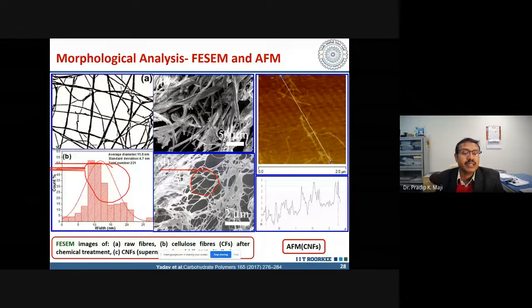Then we have done morphological analysis and diameter calculation. Average diameter we have come up with is 11.8 nanometers, with standard deviation 4.7. Total number of samples we have taken is 221 by the image analysis process. Also, we have checked with the atomic force microscope to see what is the thickness of this material.